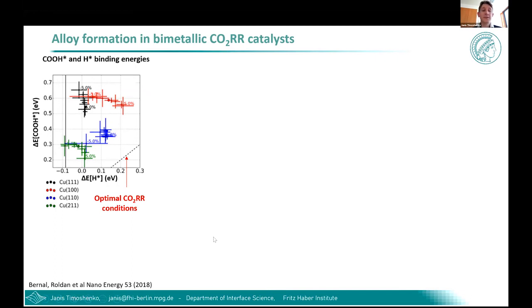And guided by DFT simulation, we can also find such interatomic distances which favor specific adsorption energies for our key reaction intermediates for CO2 electroreduction, and we can predict for which composition of alloy we should see the most pronounced CO2 electroreduction activity. However, it's important to note that all such predictions or the actual presence of such bimetallic alloy motifs should always be validated by experimental measurements, since both alloying and de-alloying can take place under reaction conditions.